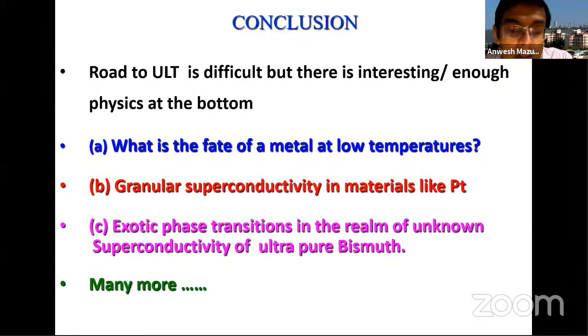Okay. Then somebody has asked that even though silver is a very good conductor at room temperature, why doesn't it become a superconductor? Good question. Copper, gold and silver. The resistance is low because the scattering from the phonons is much less in silver compared to the rest of the metals. If the electron-phonon scattering is less, the lambda, the electron-phonon coupling, is very, very small. That is the reason silver is predicted to be a superconductor at sub-nanokelvin, around 20, 30 picokelvin. So silver and copper will never superconduct.